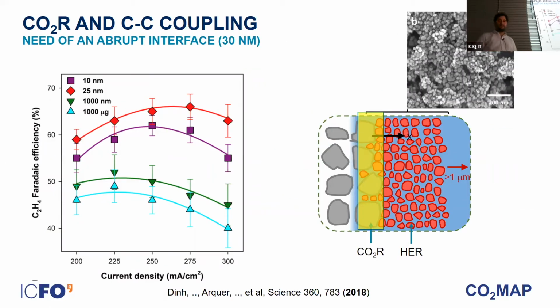Once we learned this, we then wanted to look at other figures of merit, such as productivity, such as current. And we learned that only a small region of this gas diffusion layer of this electrode was responsible for carrying out the CO2 reduction reaction. We learned that only the first tens of nanometers, around 10 to 20 nanometers of the catalyst, were doing the right reaction, the reaction we want, and the rest of the electrode was doing hydrogen evolution. So that means not sufficient CO2 was reaching catalytic sites in this case.